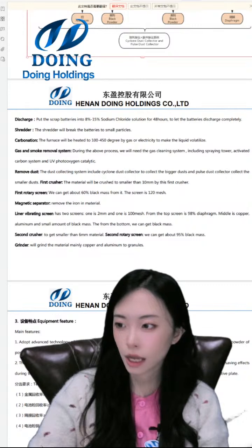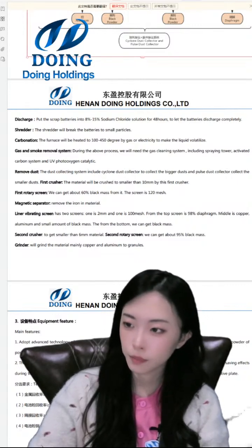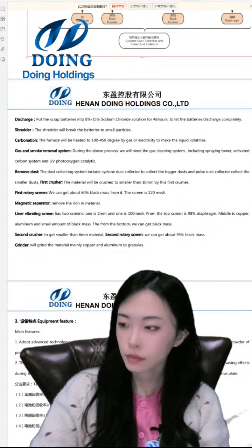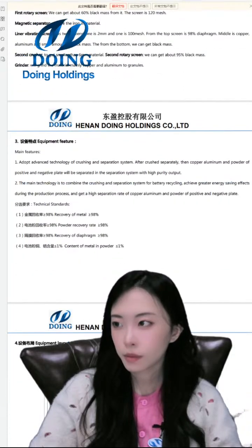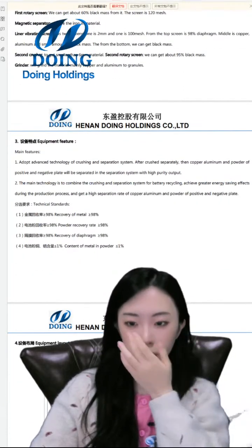Then the second crusher is also the hammer blade crusher to get the materials smaller than 6 mm. The second rotary screen, we can get about 95% of the black mass. Then the grinder will grind the material, mainly copper and aluminium, to granules. These are the different steps and the equipment features.